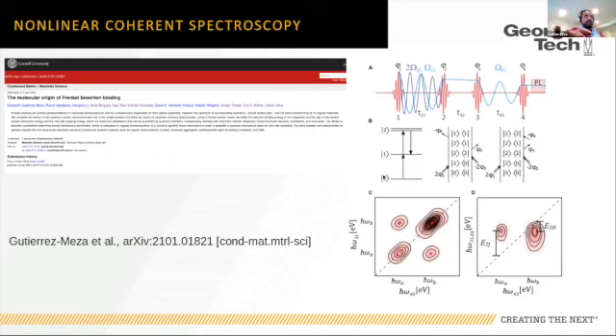And what I'm going to be looking for is, if I excite coherently a two-quantum state, what is the photoluminescence excitation spectrum of that two-quantum state versus a one-quantum state. And so what are the spectral line shapes that I'm looking for? In this two-dimensional spectrum, let's say that I have two transitions, 0,0 and 0,1, that's a little bit different from what I'm going to be seeing in a minute, but let's say two transitions, and I just do a regular 2D single-quantum experiment, I'm going to see one resonance. They're correlated because they have a common ground state, so I expect to see a cross peak between these two. So this diagonal, one energy versus the other energy axis, are the resonances that I see in linear spectroscopy, but I also see correlations that they share a common ground state, for example.